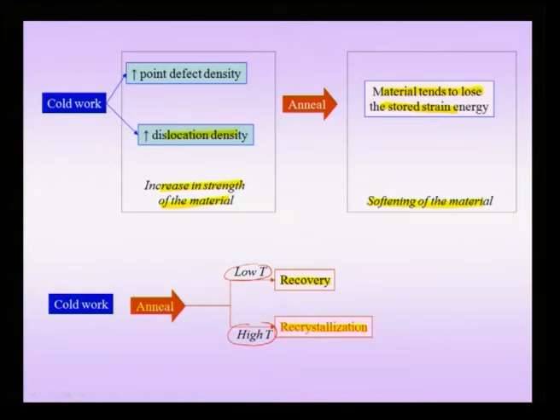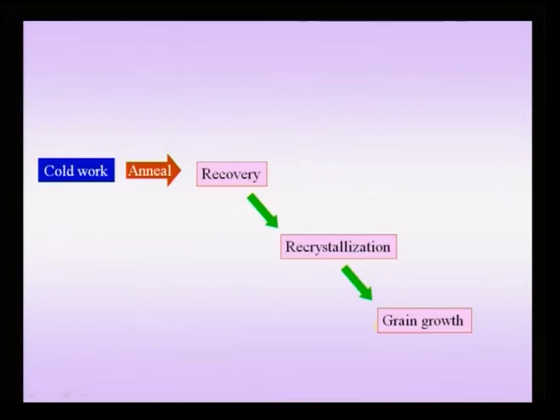And after the material has been cold worked, if you heat it to a certain high temperature and hold it, then there are two kinds of process taking place within the material depending on the temperature to which you heat. One, at low temperatures you have recovery, and at higher temperatures you have a phenomenon known as recrystallization. Now, therefore, during annealing, if you give sufficient kinetic energy, suppose you are holding at high temperatures, you would have recovery followed by recrystallization followed by grain growth.